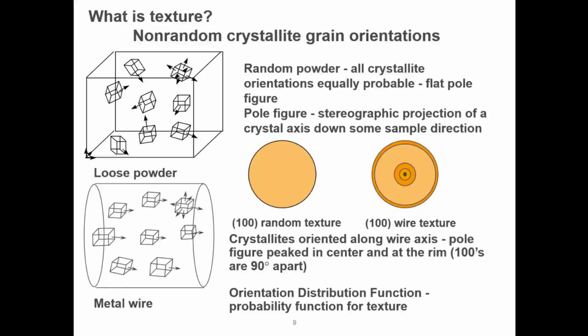Now, this may be because the powder grains themselves have a shape to them. Pack them, they pack according to the shape some way. And you're sort of then presented with a sample. Grain orientations aren't uniform. Or it may be a piece of steel that's been rolled in a rolling mill, and the rolling action induces a texture in the steel. And that's actually of interest to people, because they want to know how textured it is, for various reasons, because it affects all the physical properties of the material, depending what the texture is.